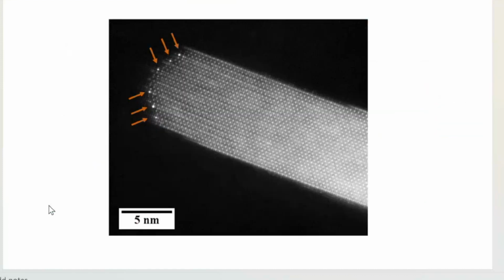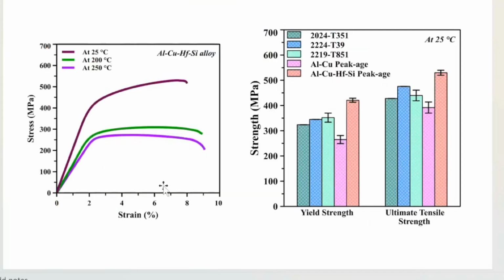To prove this point, we therefore again did imaging of the tip of a growing aluminum copper hafnium silicon plate. And here you can see hafnium has a high atomic number. So zirconium has segregated at the broad interface, but you see very bright atoms at the tip. And this is hafnium, which is stopping its lengthening, and therefore it does not coarsen at all. And as a result, you get very high strength, even at 250 degrees centigrade, close to 250, but it is not as good as tantalum. So we think that tantalum is the alloying addition at the moment which is probably the best, together with zirconium.